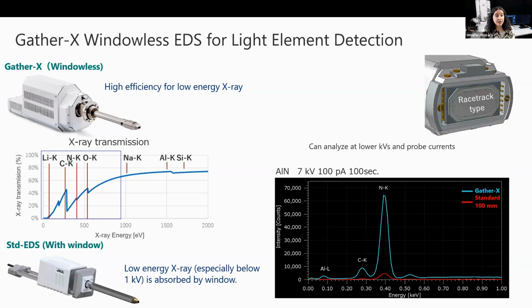This spectrum on the bottom right is comparing the sensitivity of the Gather-X below 1 kV to a comparatively sized standard EDS detector at only 100 picoamps. You'll notice not only significantly more signal, but also that we can resolve lower energy X-rays, including the aluminum L line, shown here, which is absorbed by the window in a standard EDS. And what that sensitivity translates into is not only the ability to detect low energy X-rays, including lithium, but also the ability to analyze samples at much lower probe currents and lower accelerating voltages.